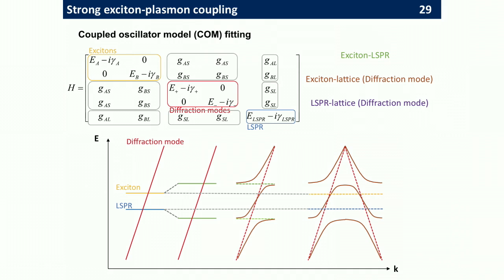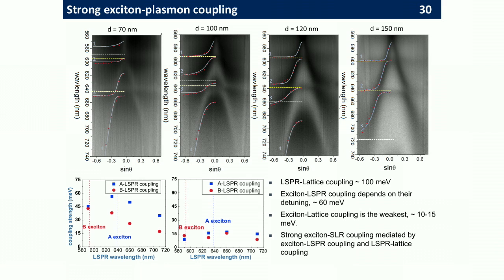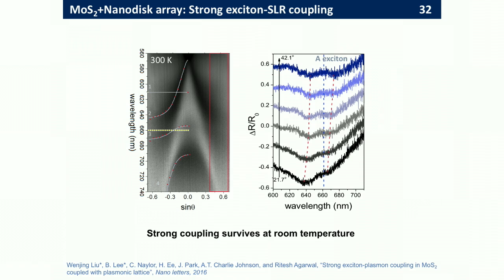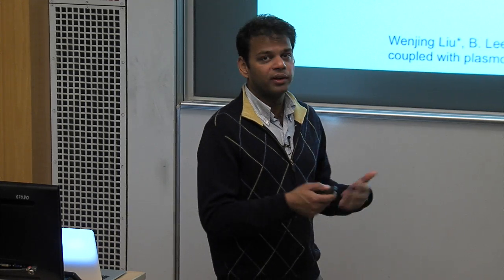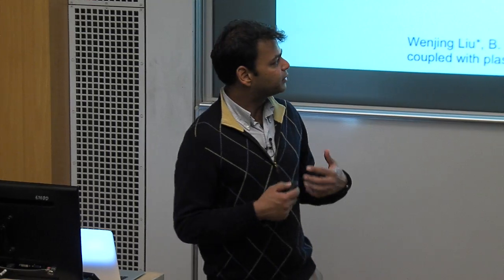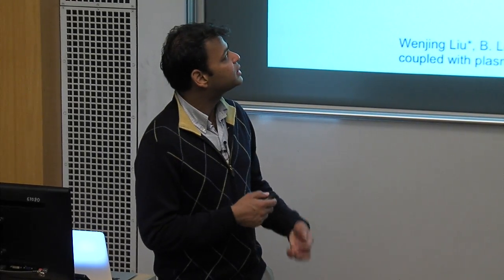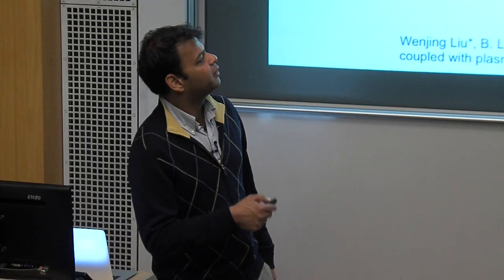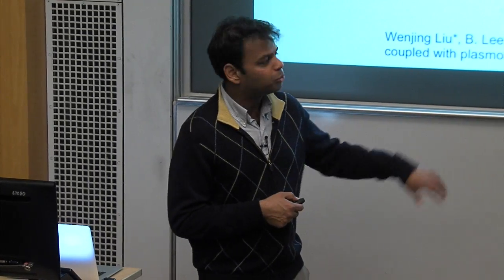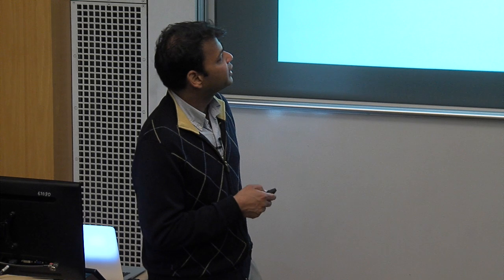This is the diffraction mode that we have, which is the propagating plasmon. Now we couple all these things, and we get this anti-crossing type behavior. This is exactly what we see in experiments. From the fitting, we can extract all these coupling strengths. Interestingly, this is a consequence of weak screening in these materials: the exciton binding energy is of the order of a few hundred meV. So it can survive at room temperature, with very strongly bound excitons, and because of that you can get this polariton behavior with plasmons even at room temperature. That was very exciting.